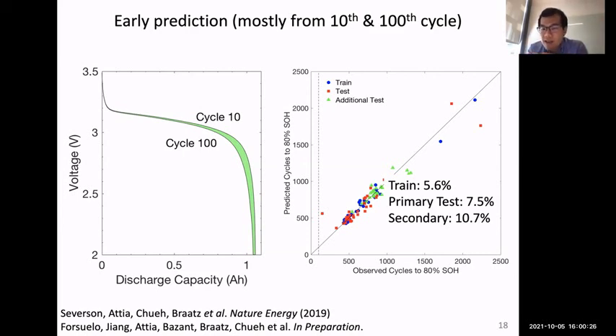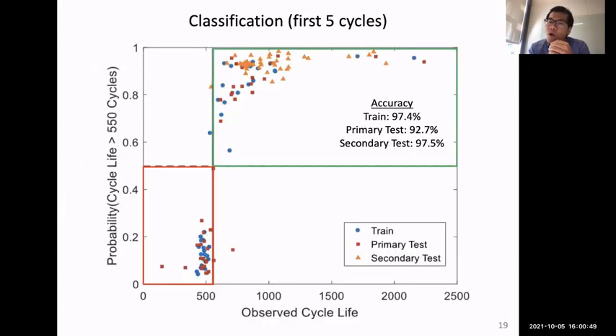Again, I think this is quite exciting because it only takes about 4 days to run the test to make this early prediction, while the batteries will last a lifetime on the order of 3 to 6 months. So this is a tremendous saving. And the reason we're able to look into this is by zooming into the voltage characteristic evolution rather than just the capacity evolution. We're also able to do not only quantification, but also classification.